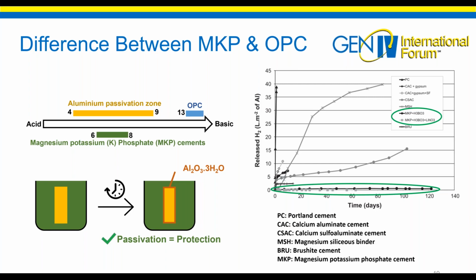The work of Codicu et al. shows that many cementitious matrices are not compatible with the incorporation of metallic aluminium, since the quantity of dihydrogen produced is in the order of several liters per square meter of aluminium. Only the phosphate cement shows very good results. They are even improved by the incorporation of a corrosion inhibitor. How to formulate the phosphate cement?